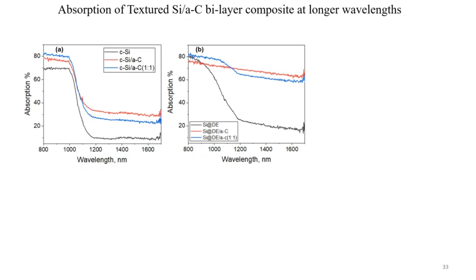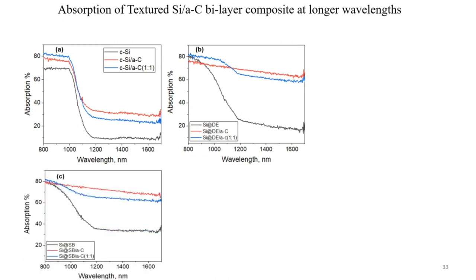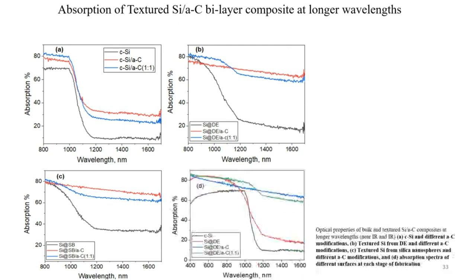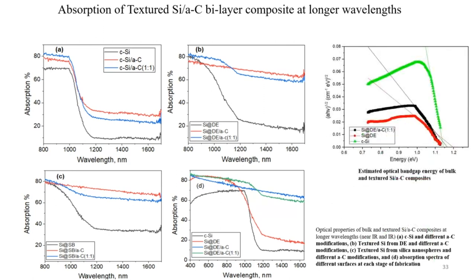The same can be seen for the textured silicon surfaces obtained from silica spheres, and a comparison of all four surfaces is shown here. So initial analysis of the optical band gap energy also confirmed a slight increase in the optical band gap for the textured silicon surfaces obtained from the in situ magnesiothermic reduction